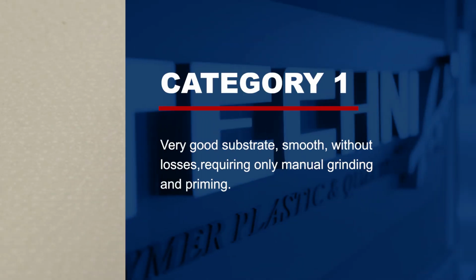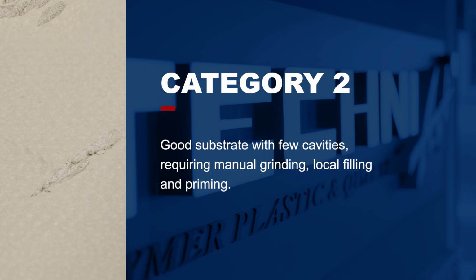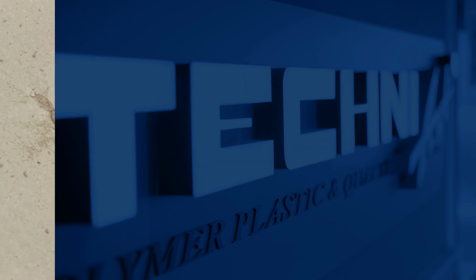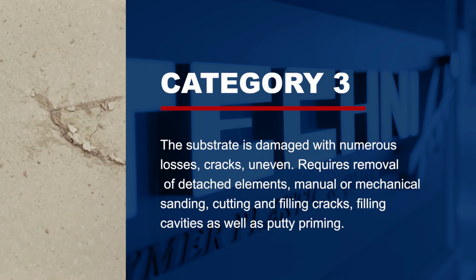Category 1, very good substrate, smooth, without losses, requiring only manual grinding and priming. Category 2, good substrate with few cavities, requiring manual grinding, local filling and priming. Category 3, the substrate is damaged with numerous losses, cracks, uneven. Requires removal of detached elements, manual or mechanical sanding, cutting and filling cracks, filling cavities as well as putty priming.